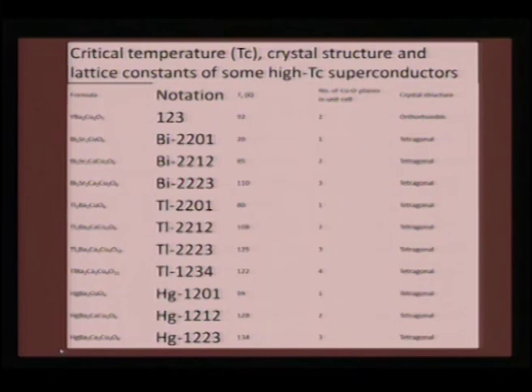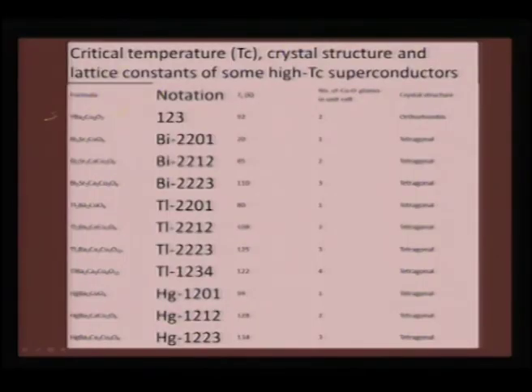Now, having said that, we can actually map some general behavior in all the high Tc superconductors that are reported. For example, you take the 123 compound YBa2Cu3O7, and from there you can see there are 3 other compounds which are mentioned. Those are bismuth related compounds, but they are nevertheless cuprates, and bismuth related compounds actually show an increase in Tc, and if you compare the Tc with the number of copper oxygen planes in the unit cell, you would find out that with increase in the copper oxygen planes from 1 to 2 to 3, the Tc is actually increasing from 20 to 85 to 110. So, this is a very clear proof that copper oxygen planes are very critical for superconductivity.